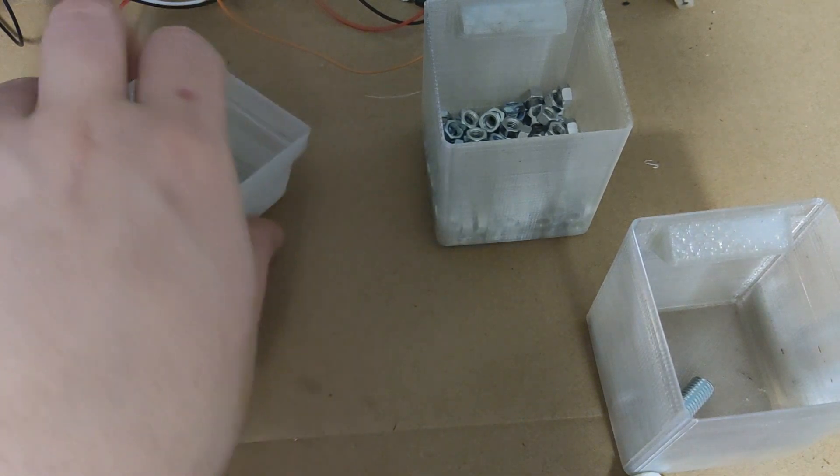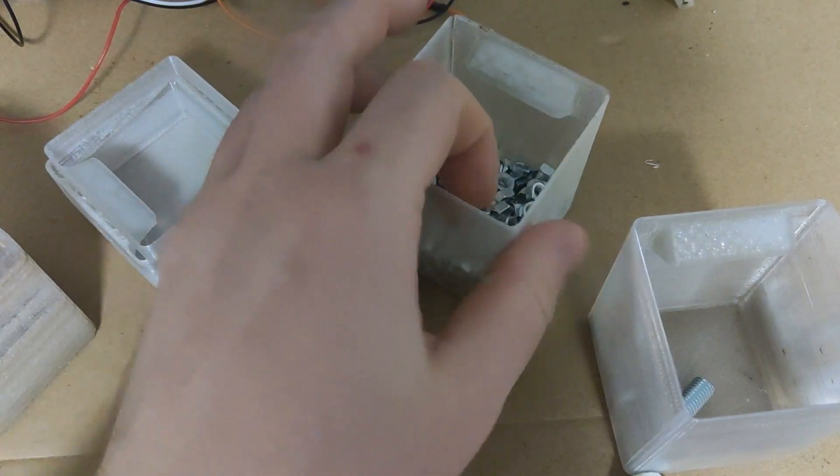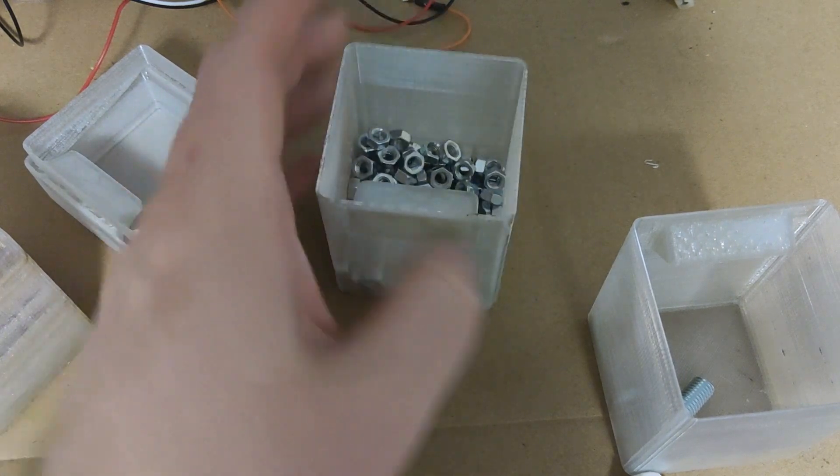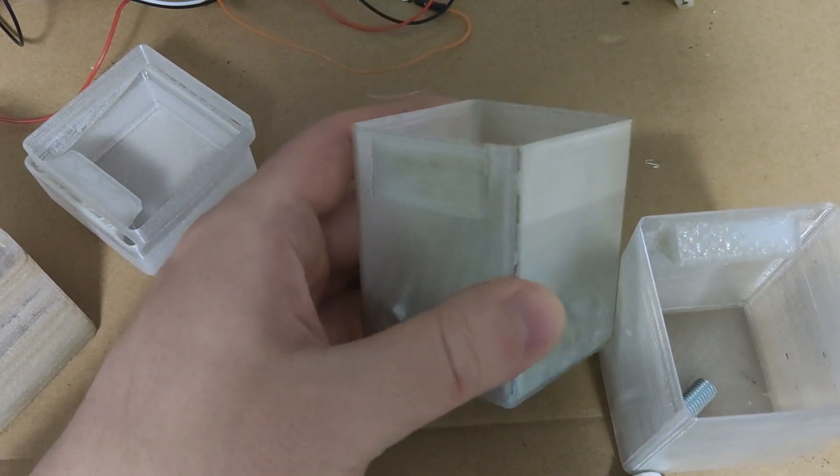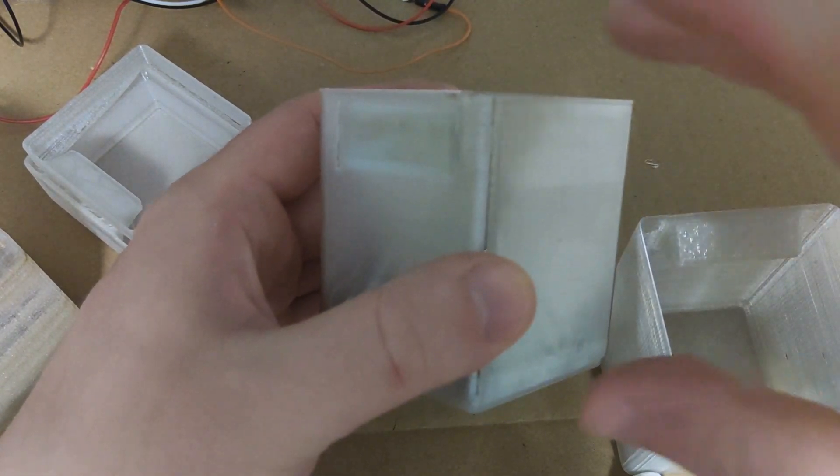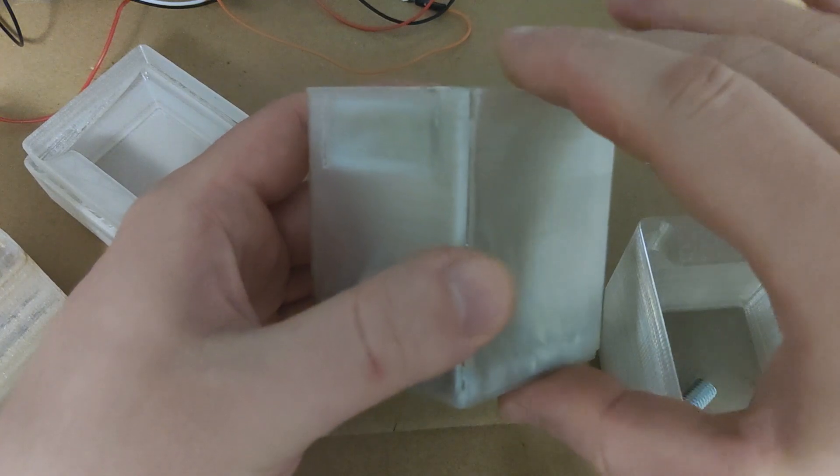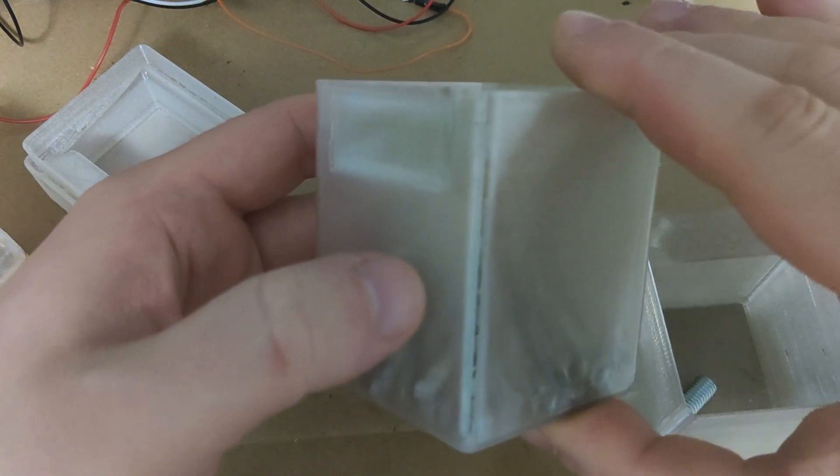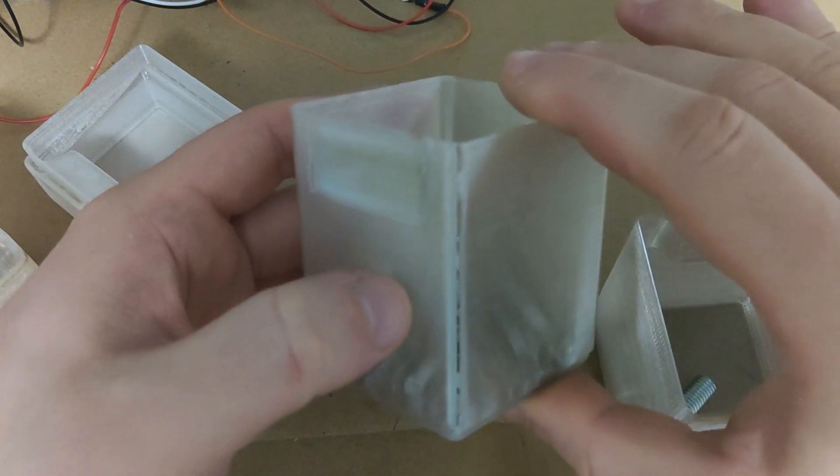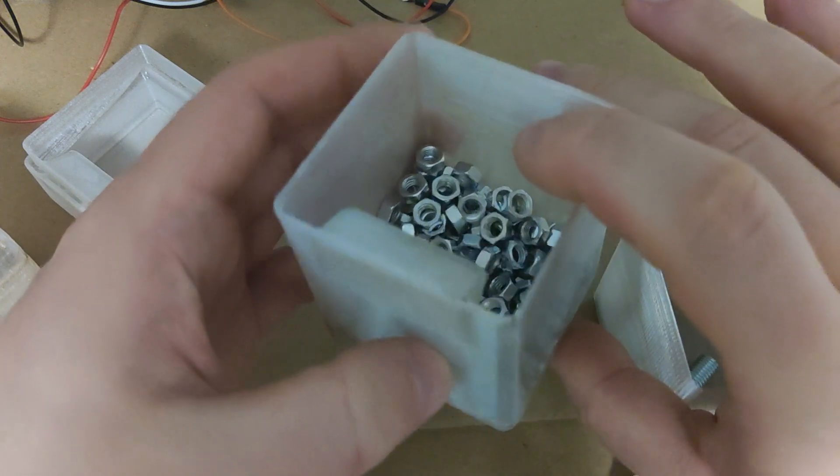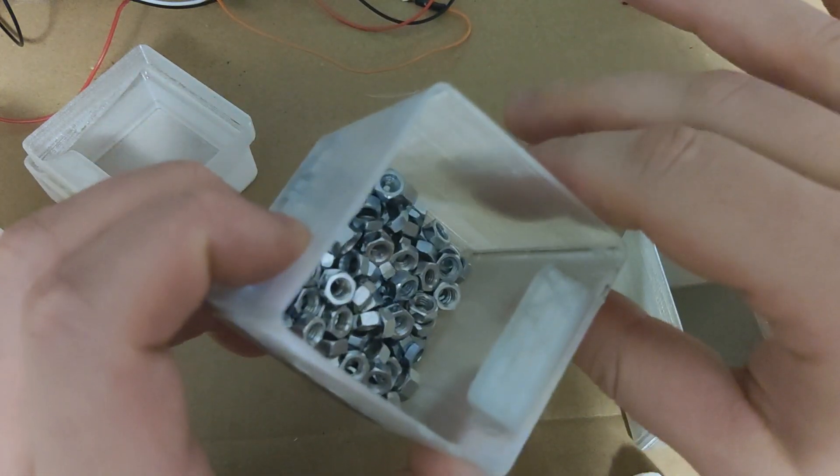Example number three is a box printed with pressure advance turned on. In Marlin this feature is called linear advance. Value I have used was great for printing PLA, but for PET it left a hole where the seams were supposed to be.